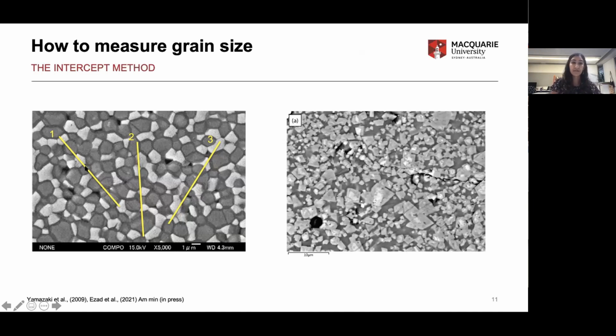and from there you can work out diameter. This works really well in cases where you have fantastic exposure of grain boundaries at high angles. Often people will put a little bit of acid to etch out those grain boundaries and really enhance their visibility. For my texture, this clearly wasn't going to work. I didn't have a lovely uniform euhedral shape everywhere. And to make problems worse, where do you define where one grain stops and another one begins? So these are the kind of problems that I was coming up with when I initially started trying to interpret grain size.